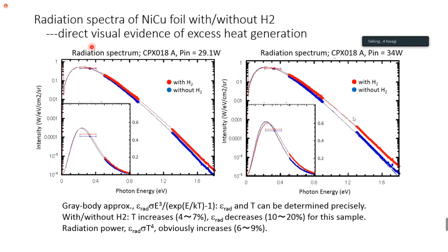So this is the result of our nickel copper multilayer. Two spectra for the different heater input power. You see the blue spectrum and the red spectrum. Red one is, of course, with hydrogen, red H2. And the blue one is without. You see the increase of intensity in whole regions, including the very low energy region. And if you increase the heater input, the similar, but a little bit more intense for this region.